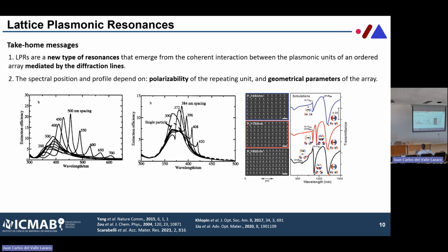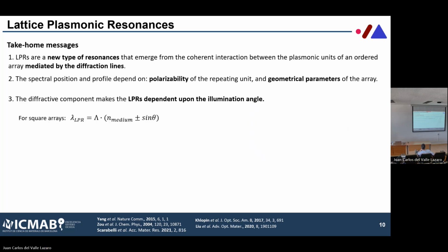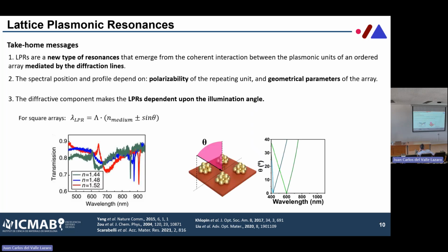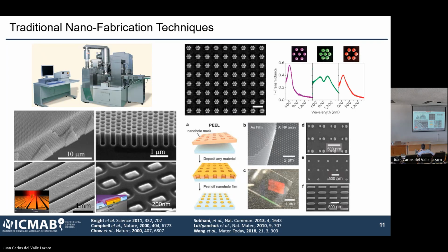So as you can see here, I can have a more complicated response. And then finally, since there is a diffraction component here, there is an array, okay? These resonances are angle dependent, so will depend on the illumination angle that I use to illuminate the system, okay? And so you can see here basically how these can change, and of course they are also dependent on the chemical environment.